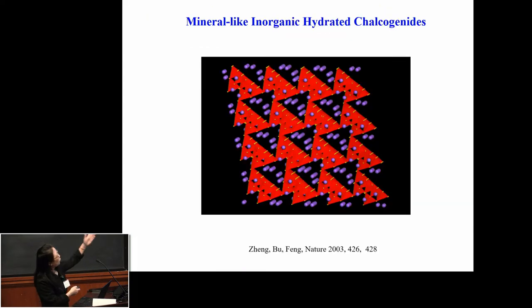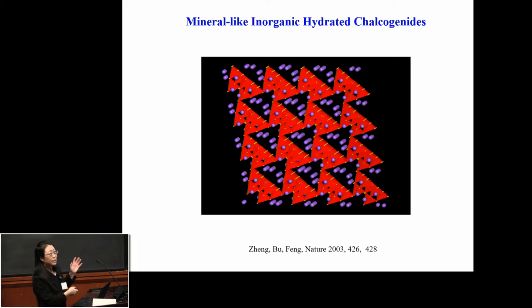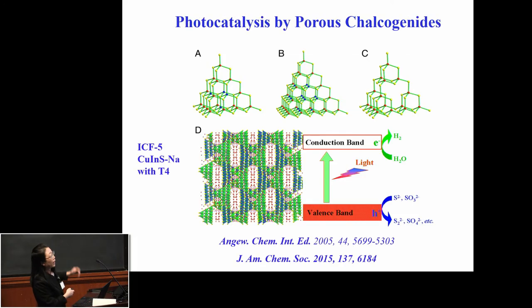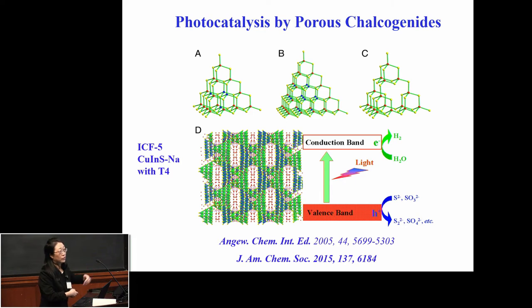With the negative charge of the cluster, we can introduce different cations such as lithium, sodium, or hydrogen cations. These cations can move very fast, giving the material fast ion conductivity — actually the fastest among crystalline porous materials. This enables different applications. Because we have both semiconducting properties and porosity, this material can be used as a photocatalytic material, with water directly in the pores and a high active surface area, to convert water to produce hydrogen.